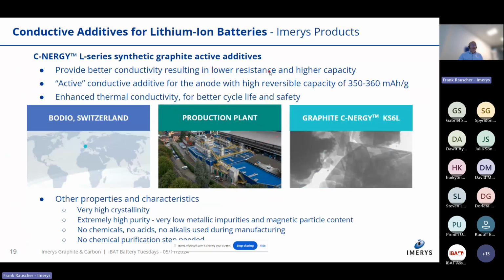Highly crystalline materials, highly conductive. It's actually an active additive because, of course, it has a reversible capacity at low rates. So we sell it as an active conductive additive. And it also offers things like thermal conductivity, which is important, especially for applications where you charge and discharge your battery at higher rates. And if you follow the industry, especially for EVs, one of the things that lithium-ion battery companies are targeting are faster charge rates to allow you to quickly fill up your battery to continue travel on a highway.